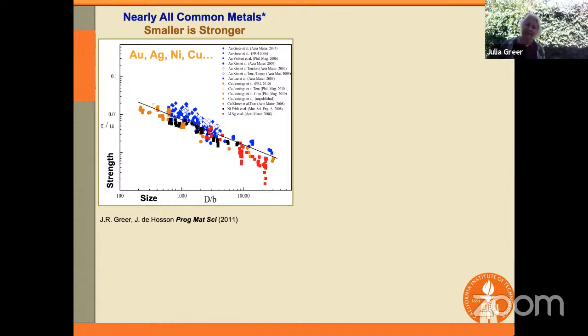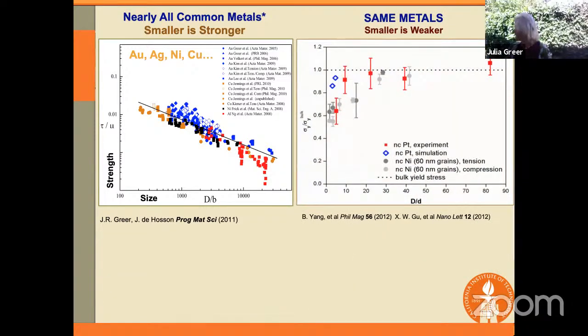And what that tells us is that if you take a very malleable piece of gold and reduce its dimensions to about 200 nanometers, it becomes as strong as steel. Okay, so this is the example of a size effect of smaller is stronger. Now, if you take exactly the same metals and change their atomic microstructure such that they now contain grains and grain boundaries, all of a sudden you see that this effect is reversed and smaller is now weaker.